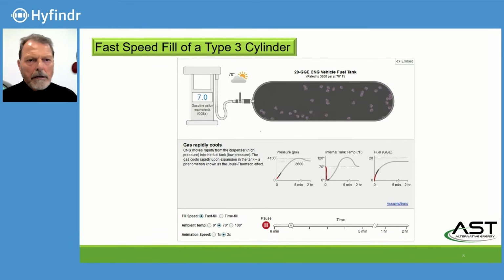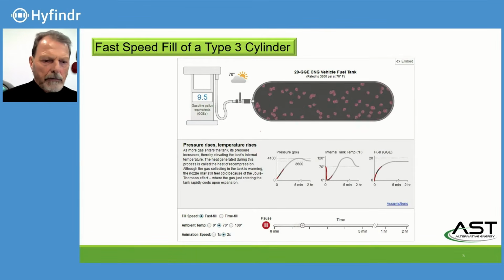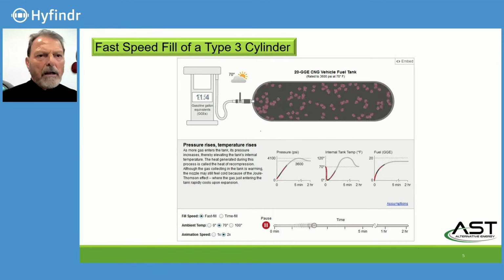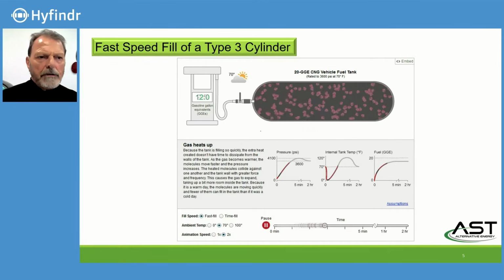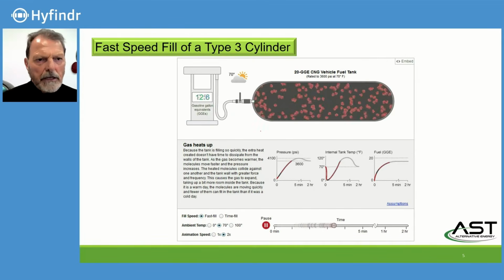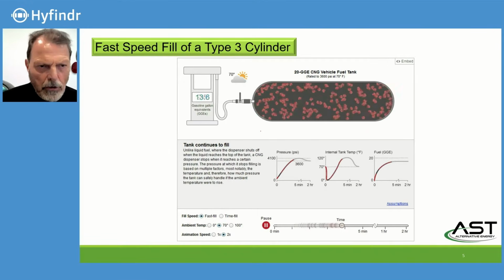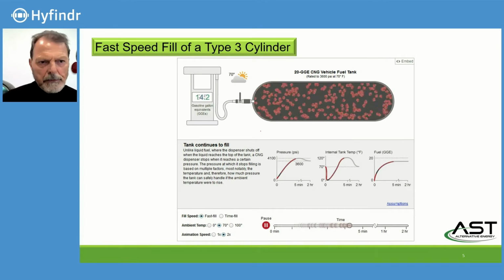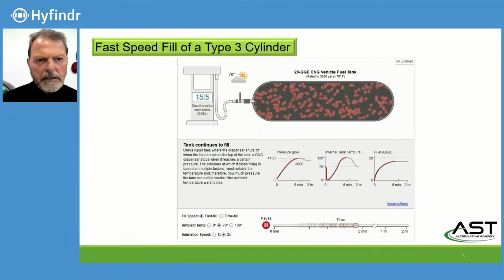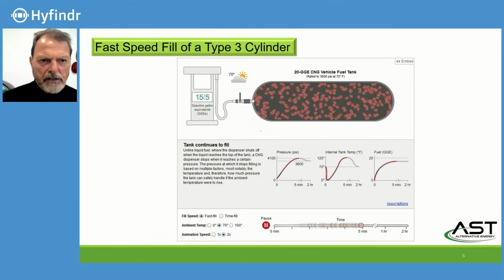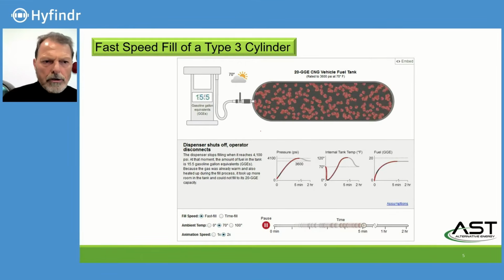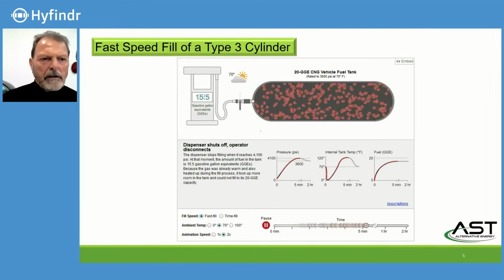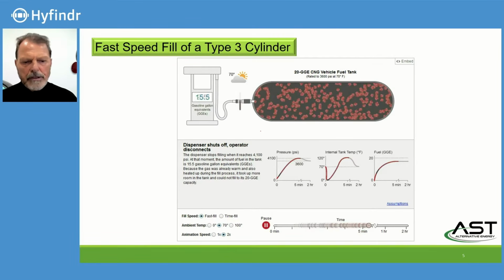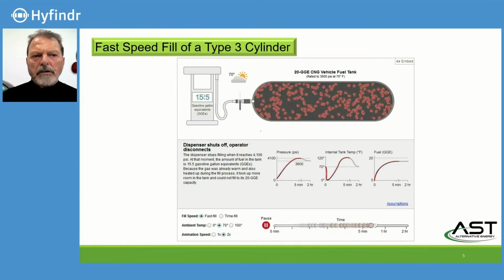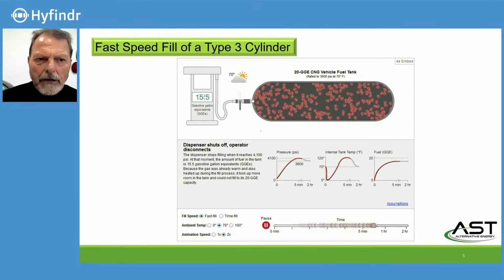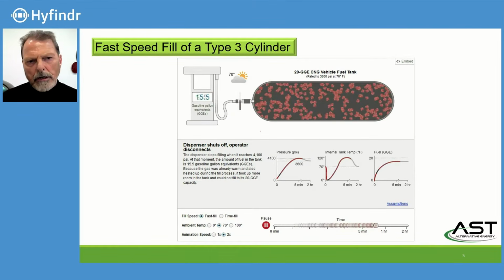When you see the filling rate here, this is a CNG application. It's a tank with 250 bar, that should fill to 20 gasoline gallon equivalent. And when you see the fill rate on the left side on the station, during the filling process, the molecules start colliding with each other at a very high speed. At the beginning, the temperature goes down, as you can see in the middle graph below, and then the temperature starts to rise fast as the pressure goes up. So you can see on the left graph below that at 4,100 psi, which is about 285 bar, the station shuts off for safety reasons.